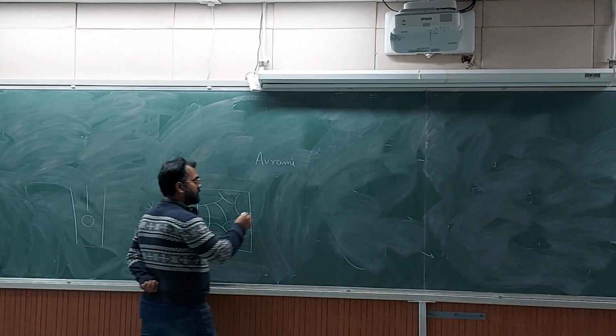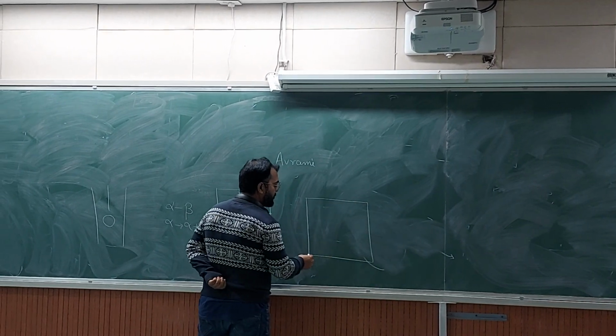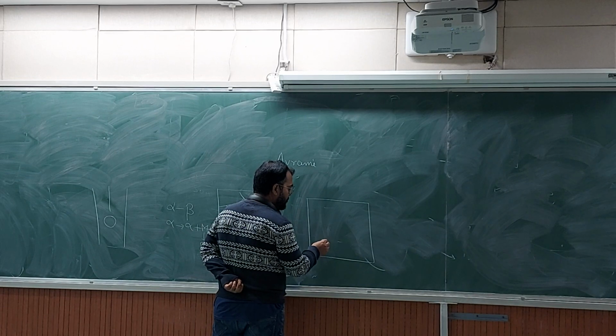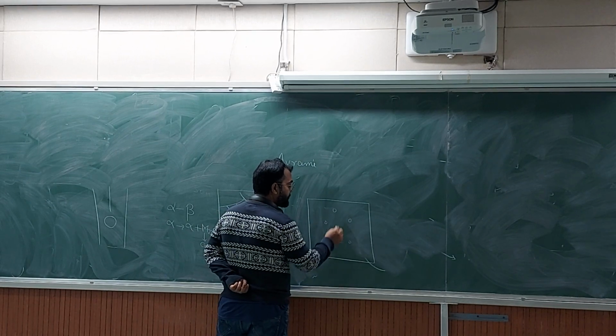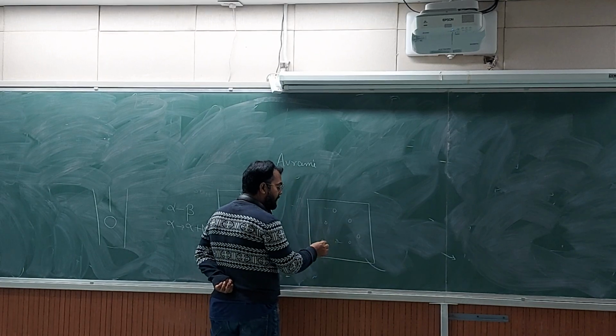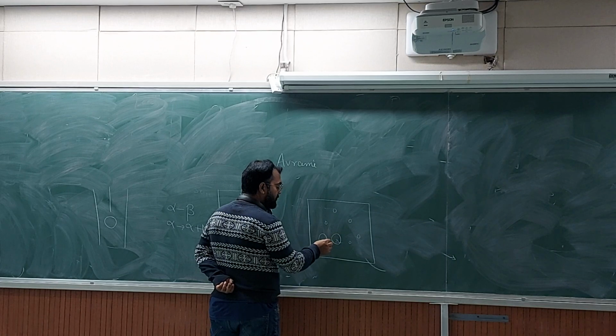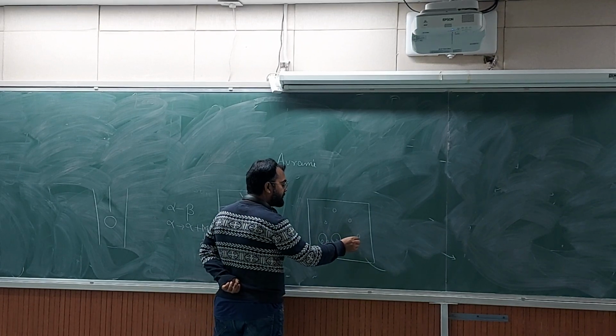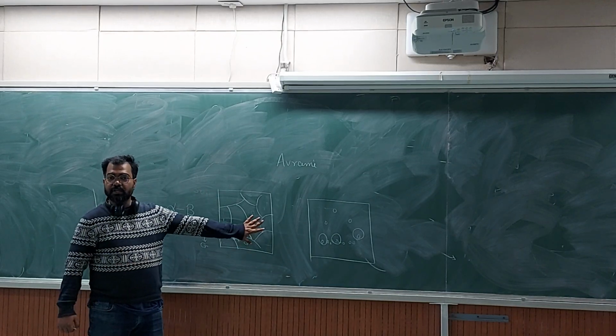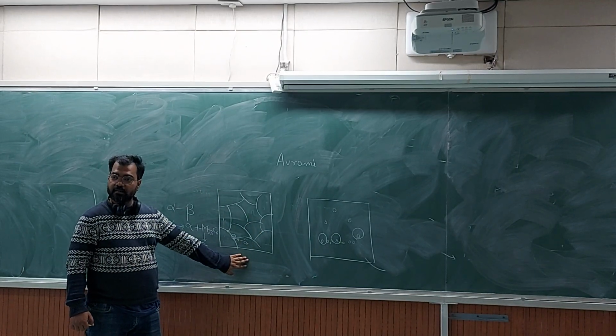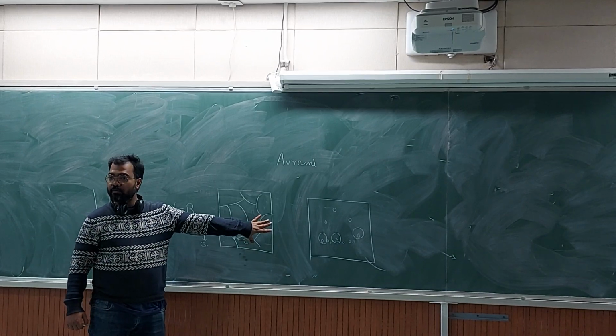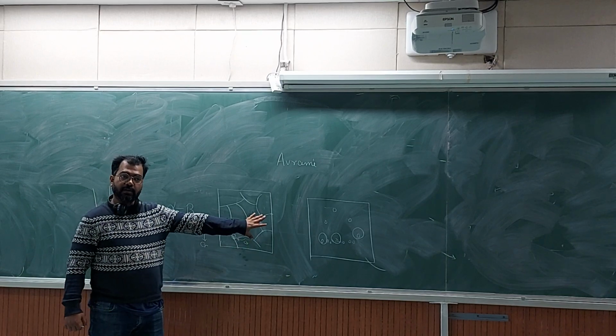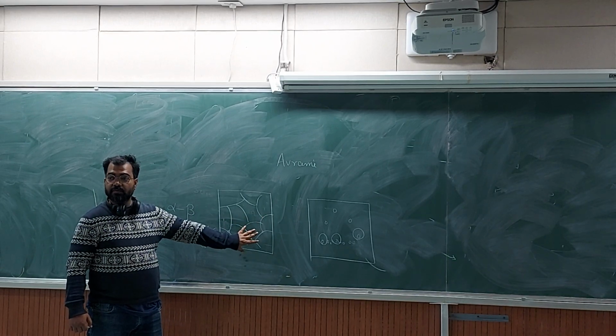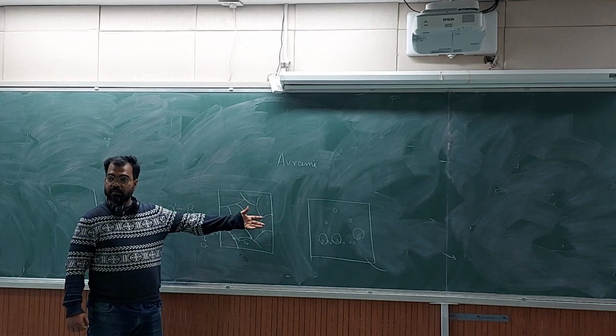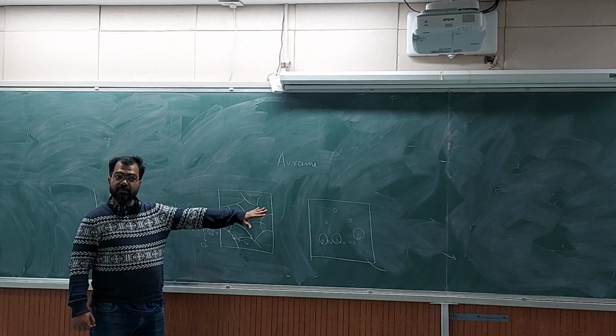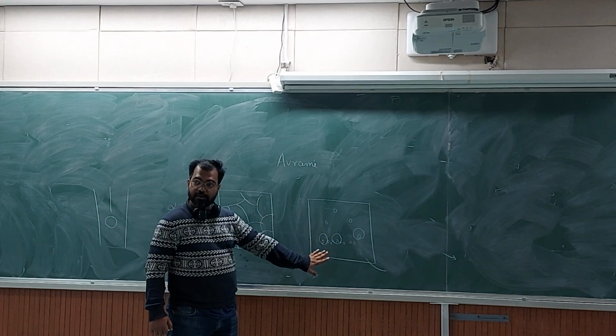And what happens in ductile damage is that you have nucleation of voids, and these voids are first nucleating and then they grow, and when they grow there are other nucleations also. So this part is same, this picture is same as what is happening in precipitation. You have nucleation of precipitates, you have nucleation of voids. You have growth of precipitates, you have growth of voids. While you have growth of precipitates, you have more nucleation of precipitates, right? Same thing is happening there also. So when you have growth of void, new voids are also nucleating.